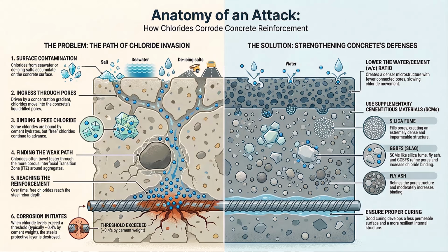It does, because of the sheer volume of high-value coastal infrastructure. I mean, the man-made islands, the massive ports. UAE specifications have been forced to adopt the highest performance targets as standard practice. It's not optional. They frequently mandate these specialized, non-negotiable concrete mixes, typically requiring 50 to 60% GGBFS replacement, paired with up to 10% silica fume, and all combined with a strictly low water-to-binder ratio of 0.40 or less. So it sounds like the severity of the environment, plus the speed of development, has made high-performance concrete a regulatory default. It's not an upgrade. It's just the price of entry. It's mandatory durability insurance. You have to buy it.